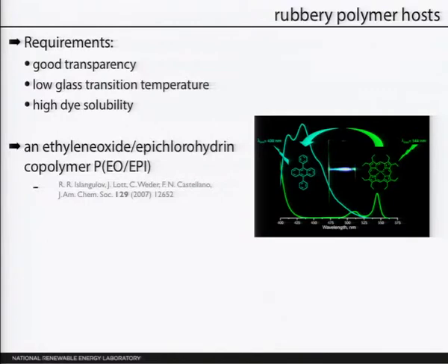This was essentially the first demonstration that this process could actually be carried out in the solid state. What I may not have made clear earlier on is that the upconversion process itself is strongly dependent on diffusion of the molecules, which is why it happens efficiently in solution. So to actually see this process occur in the solid state is pretty remarkable.